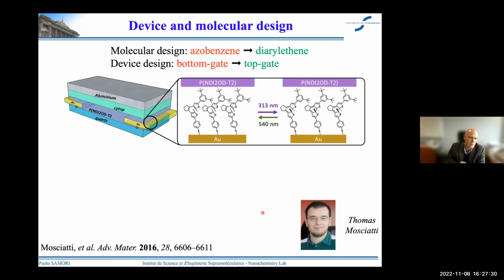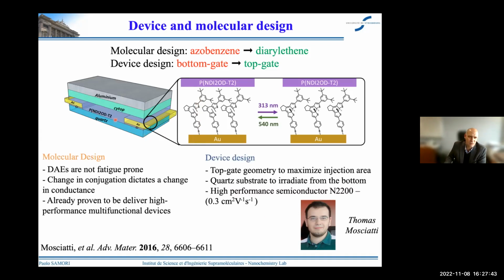And so you can see that the top gate is Cytop-based. In the junction, we put a thiolated diarylethene, and in this case we also decided to change the type of semiconductor to get a high-performance semiconductor, N2200. Again, quartz as a substrate allows us to irradiate from the bottom. In this way, the use of top gate geometry enables us to maximize the injection area.